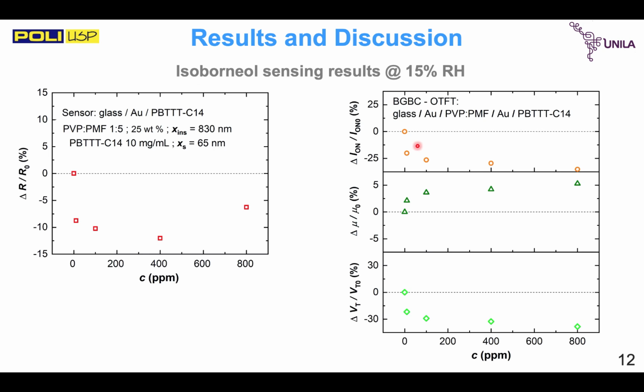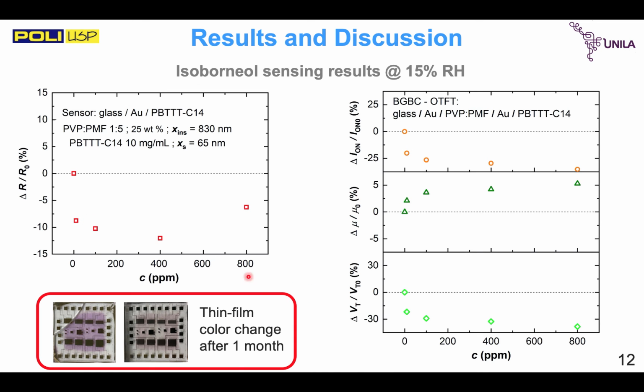It is worth saying that sensitivity at 10 ppm is already at 20% for transistors, while it's less than 10% for chemical sensors. And it is worth also saying that the concentrations used here are much higher than real concentrations in real samples, right? After 1 month, the device had been degraded, and this can be observed by the changing color of the semiconductor.